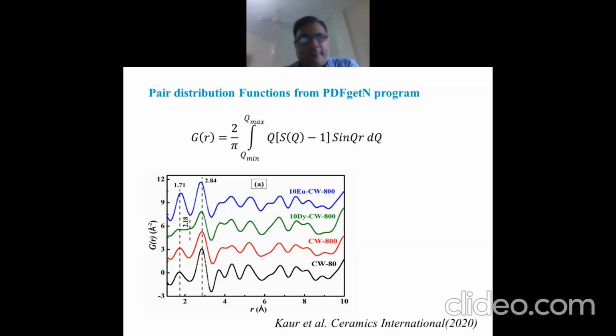So you see that the first peak, in the bottommost trace, calcium tungstate 80, is at 1.71 angstrom, and this peak exists in all the samples. These peaks are due to W-oxygen correlations, the W-oxygen bonds. The second major peak is at around 2.84 angstrom, and this peak is due to oxygen-oxygen correlations.